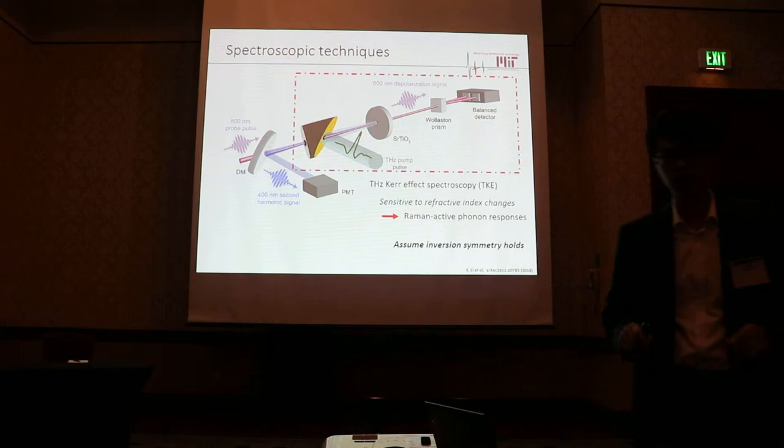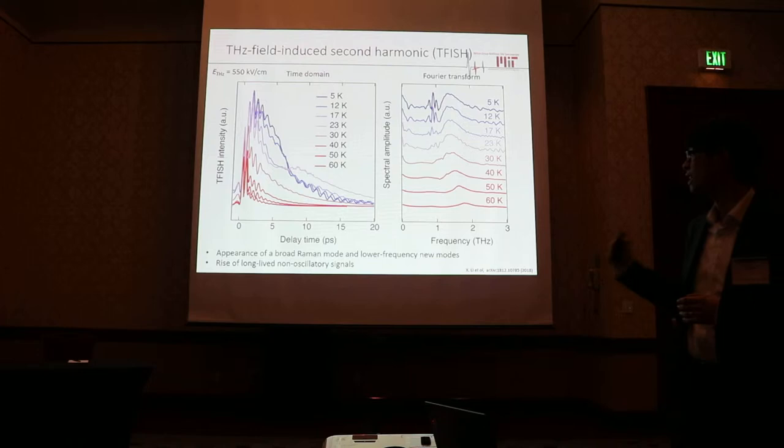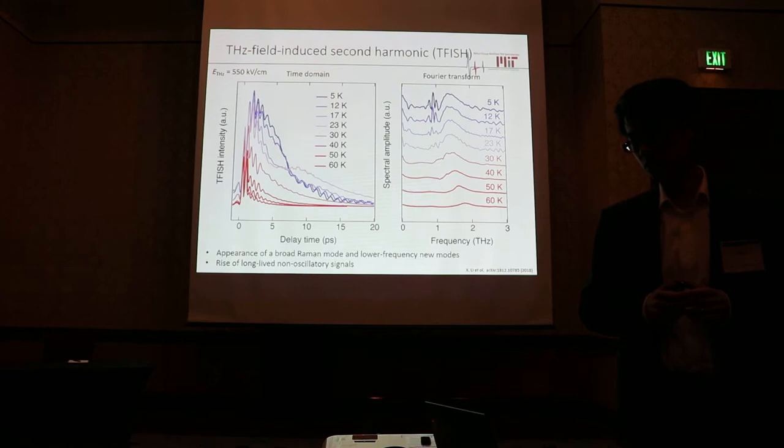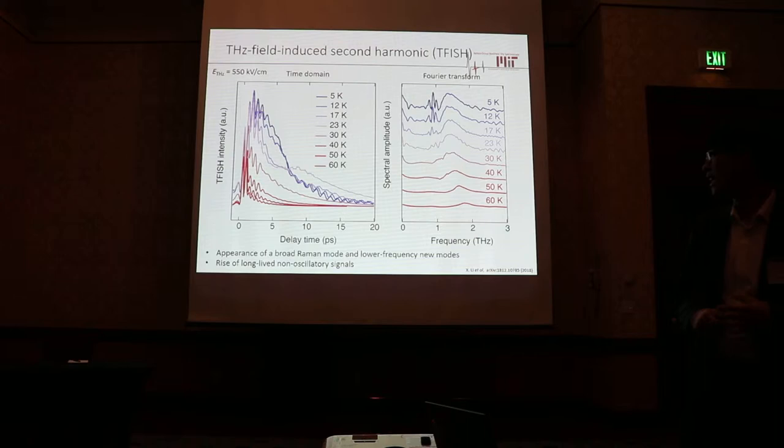Here's the temperature dependence of the TFISH signals — the TFISH time-domain signal and its Fourier transform. The phonon vibrations launched by the terahertz pulse show up in the trace as oscillatory signals, and the non-oscillatory component of the signal indicates the terahertz-induced orientation of dipoles.